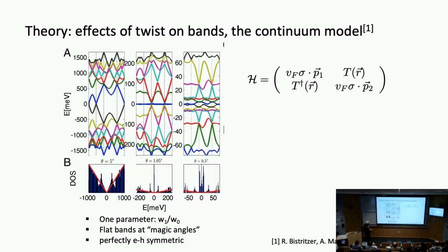The simple model that Bistritzer and MacDonald put together involves a Hamiltonian like this. Along the diagonal of the Hamiltonian are the individual graphene layers, graphene layer 1, graphene layer 2, each one of them linear in momentum, as we explained, and the off-diagonal term is the interaction. You put all this together and you produce this kind of bands from the combined system, and for very special angles, so-called magic angles, you have these very, very flat bands. These are from more realistic calculations based on the continuum model.